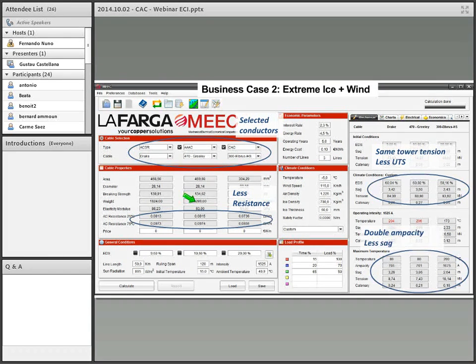And the good thing of this example is that having less resistance, the same tower tension, less UTS, we can get double ampacity, or more than double ampacity. So you can see here how we can transport double the ampacity, and the sag was less, we have less sag than the solution with the ACSR or the AAAC. So this is really interesting. You will have a line where just by installing the CAC, you will have the possibility to transport double energy.